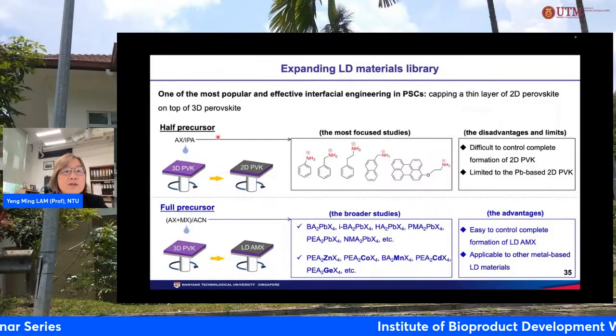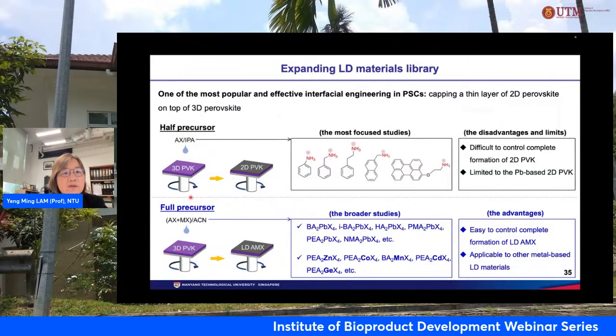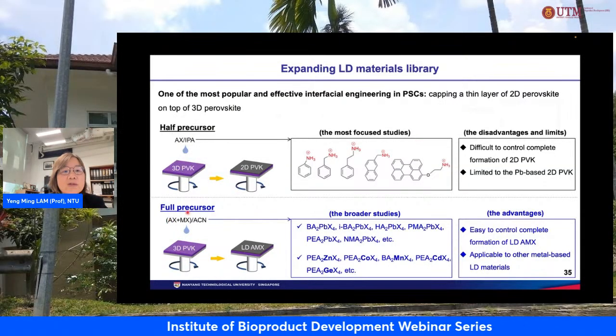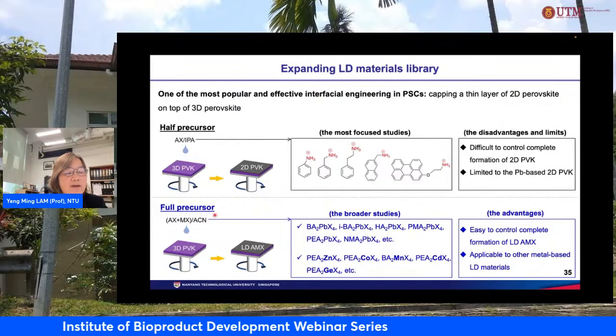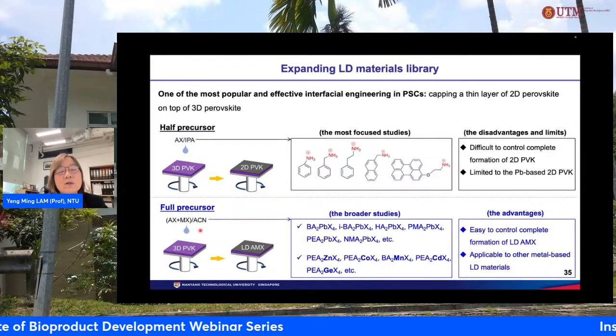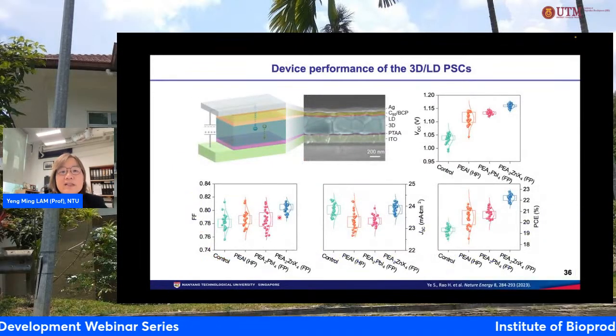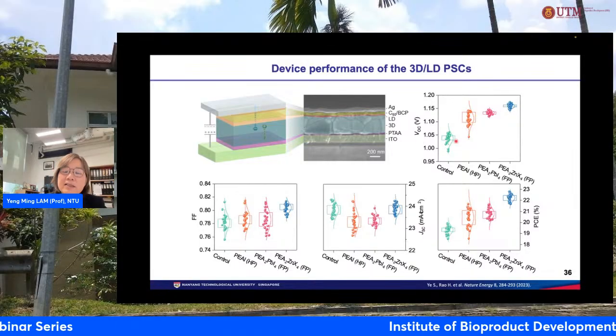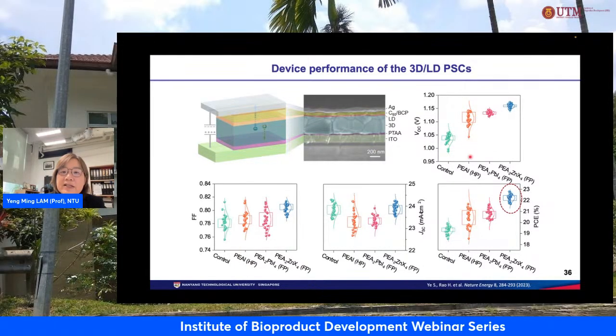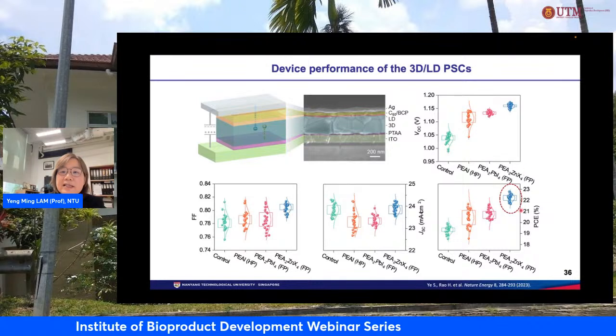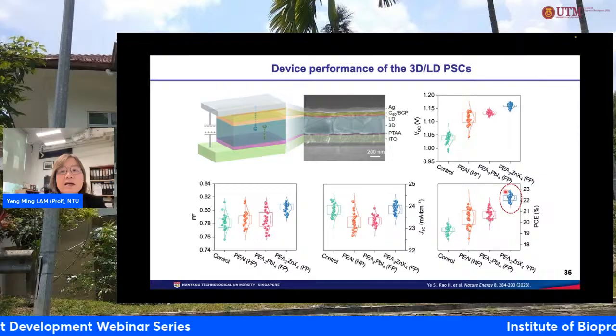So we have transformed the half precursor method to a full precursor method, and the way to do this is by using the correct solvent. With this, we can now deposit the material with various architectures, and the best thing is our efficiency. The conversion efficiency can hit very high now, above 20%.